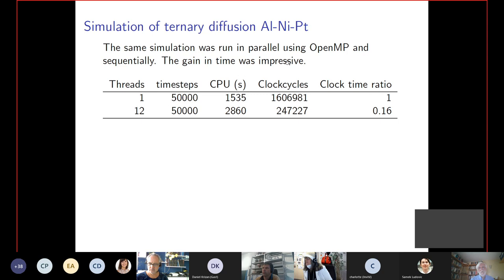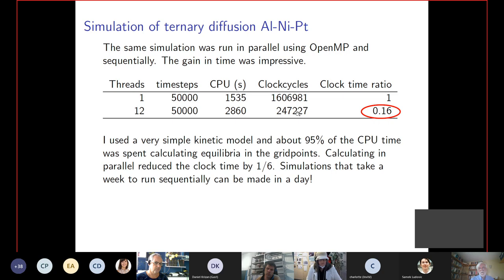I also did this with OpenCalphad, which has a facility to calculate equilibria in parallel. There is an OpenMP system where you can compile with it. I calculated this twice, once with 12 threads using 6 CPUs. And this is the CPU time for this simulation. I had exactly the same results, of course, but the clock cycles decrease quite a lot when you calculate in parallel. Basically, this is the maximum you can get. Having 12 processes, I can get 1/6 of the computational time. And this has actually been used in some applications, and it seems to work quite well.